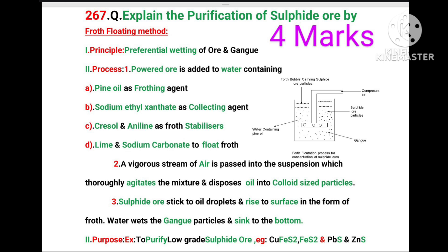Process: Powdered ore is added to water containing: A. Pine oil as frothing agent to form froths. B. Sodium ethyl xanthate as collecting agent to collect the material. C. Cresol or aniline as froth stabilizer to keep the froth for some time. D. Lime and sodium carbonate to float froths.